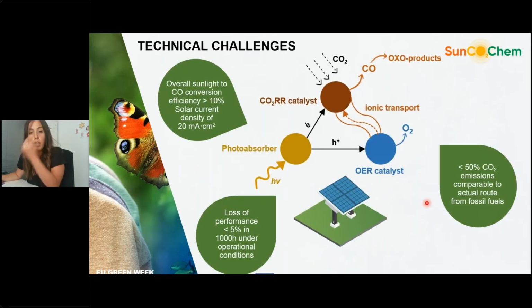And which are the objectives that we are planning to obtain with our device? We want to manufacture a device with an overall sunlight to carbon monoxide conversion efficiency superior to 10%, and that will give us a solar current density for CO generation of 20 milliampere per square centimeter. We want to manufacture a device that will lose less than 5% of its performance under 1,000 hours of operation, and that will decrease more than 50% the CO2 emissions in comparison with actual technology routes for the production of oxo products from fossil fuels.